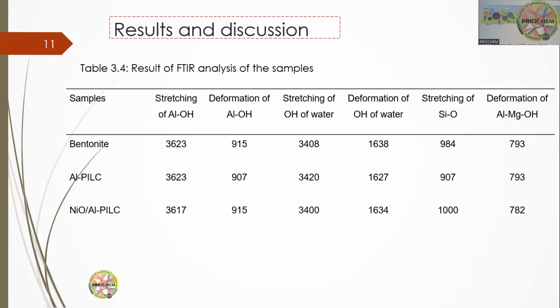Then this is the summary of the absorption bands that we get. It is telling us that in the bentonite, in the aluminum pillared clay, and in the nickel oxide, the absorption bands have appeared in all the materials, telling us that even after the pillaring and even after the doping of the metal, our main structure is there. But there is a difference in the intensity of the absorption bands on the FTIR.